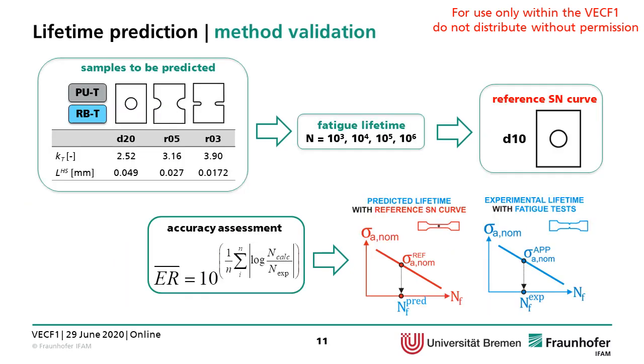The validation of this method was done considering 2 types of adhesives and 3 types of samples with 3 different types of notches, an internal notch of 2 millimeters and external notches with 0.5 and 0.3 millimeters. They have different highly stressed regions, and also they have different stress concentration factors, trying to predict fatigue lifetimes of 1,000, 10,000, 100,000, 1 million cycles using as reference SN curve an internal notched sample with 1 millimeter.